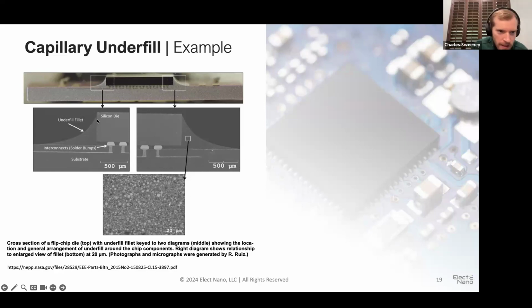But you can also see right here on the edge, there's actually a fracture that's starting to form. This can start anywhere. You can get a crack on the fillet, and that crack can propagate underneath the device. Then you can have either adhesive or cohesive failure, and the cracks work their way through the substrate and the die. If a crack forms, that can let moisture come into the system, or it can allow the stress to build up and catastrophically fail one of your interconnects.